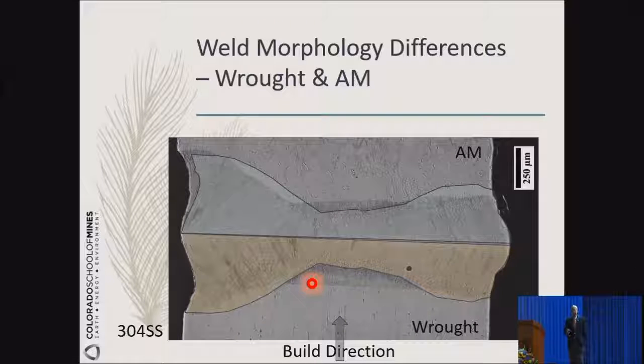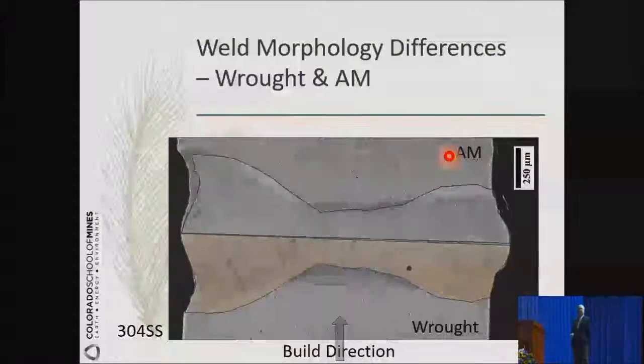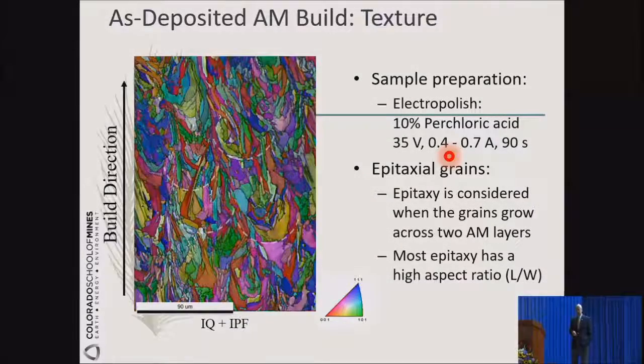And if you look at the weld morphology, basically what we did is we copied the bottom side here and just superimposed it here. Can you see that there's a region here that is not covered? There's a region not covered. So actually the weld pool that forms, I call it a weld pool, but it's the deposit pool, is different in shape. So again, this is a reminder that there are fundamental differences between the wrought material and the AM material.